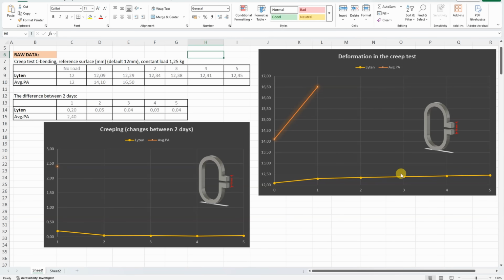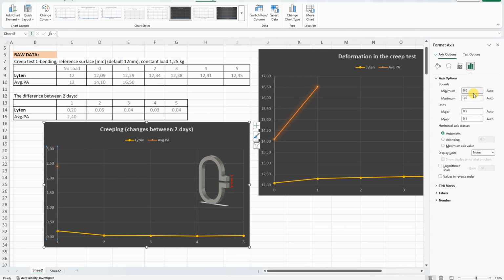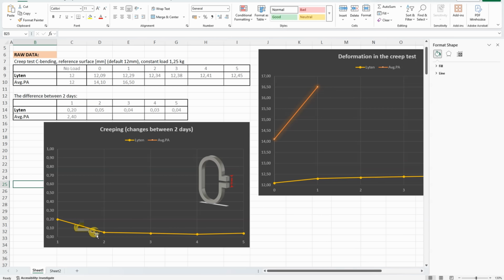On this graph we can see the distance between two reference surfaces extremely minimal on this Lyten compared to the average PA. Basically it is in the category of the PA. Let's see the creeping, which is the difference between 2 days, and it's completely deformed because of this number. Let's change this value, I don't know, to 1. Okay, so even now we can see, actually it is not completely 0, so it has that property of the nylon that it slowly creeps even on a day 5, but this is extremely minimal compared almost to any other material.